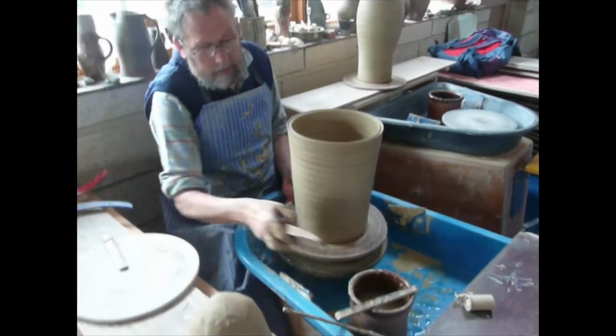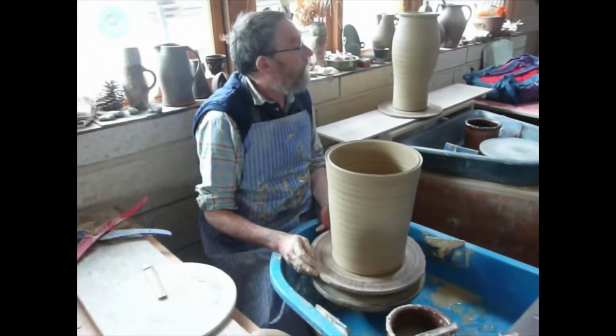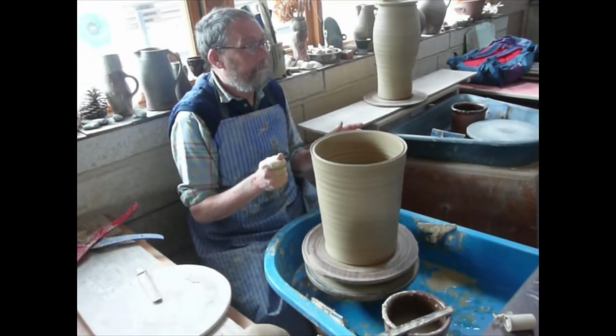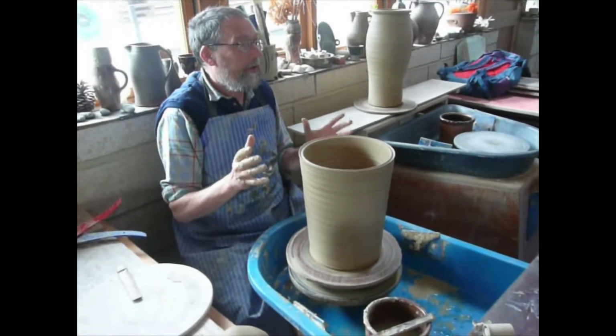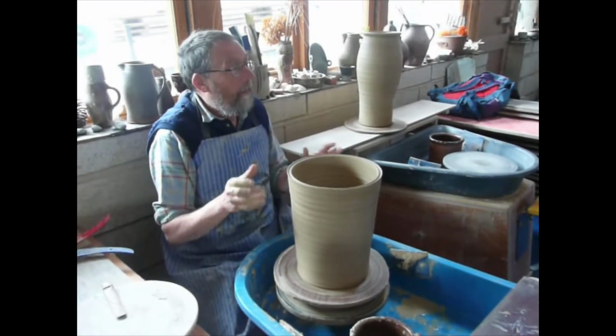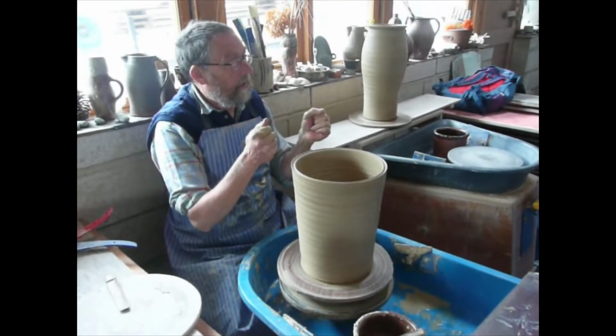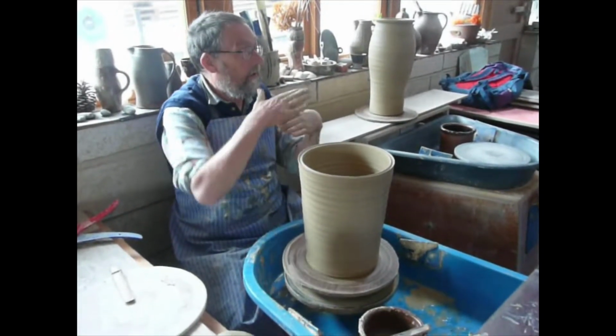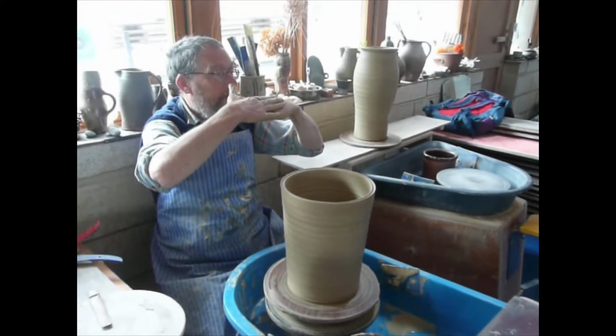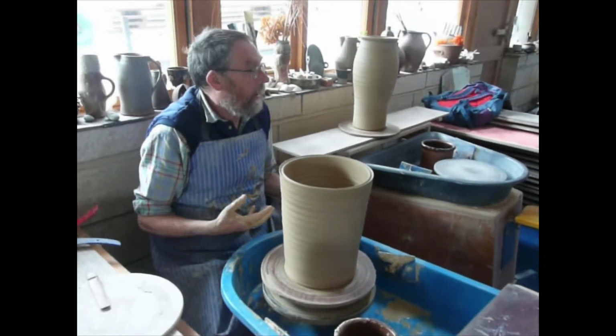I don't think I'm going to have time to do that, and I really don't know how to do it anyway, but the Chinese have this way, and the Indians do the same thing, where pots are beaten. Now, if you put two pots together at the soft and hard stage, and then you beat them into a bigger pot, the very action of that beating on that join will get it to join very solidly. So there you could put together two flat edges, and then in the beating, they come together. So you might get away with that.